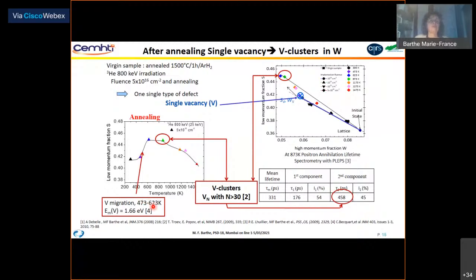around 500 K temperature. And we also measure the lifetime at this annealing temperature, and we found two components, with the longest at 460 picoseconds, which corresponds to vacancy clusters with a number of vacancies equal to or larger than 30, if we compare to the theoretical values.